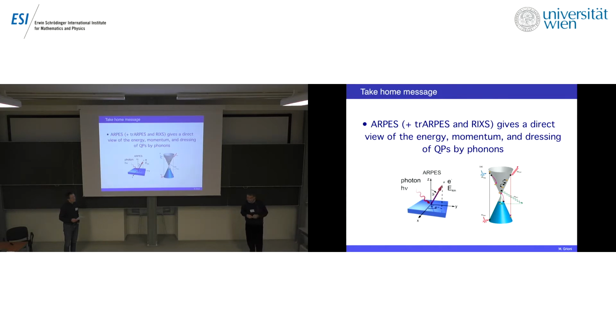Well, the problem is that it is an insulating material, so that's one problem of ARPES. The samples charge up, and then it's very difficult to do the experiment. This material at room temperature is quite dynamically disordered, and there's another complication, which is whether it's a thermal disorder or correlated disorder. So that would change the band curvature. That's a good point. Yeah, that's a limitation of our experiment, yes.